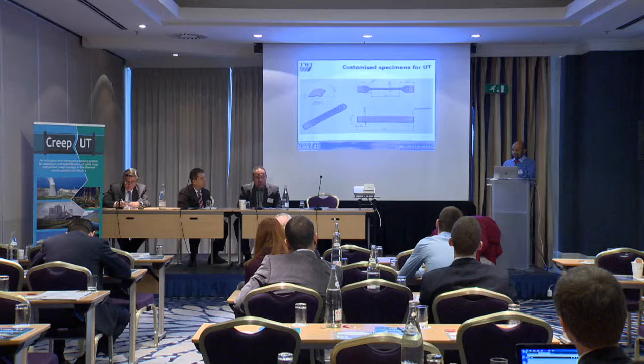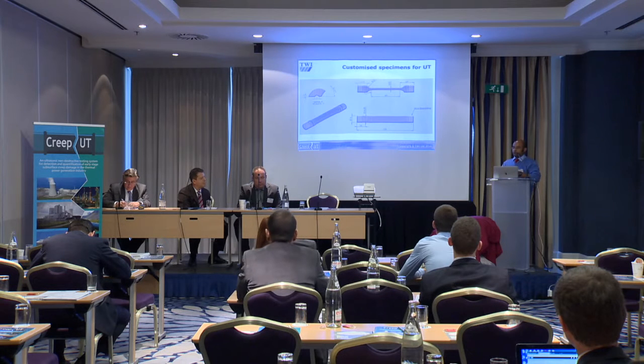So fatigue loading gives you the opportunity to do something faster. For instance, the average time to get any results from this can range from 2,000 to 4,000 hours, because you need to move the creep slowly through the secondary phase. But as part of the core research program, there is work ongoing to see if we can accelerate that process using the fatigue method, because fatigue will add stress, but you can operate at stresses which are much lower than yield, and it can possibly be achieved much quicker.